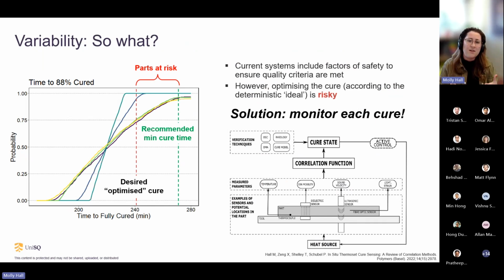Our current minimum cure time for this material, with this cure cycle, is about 275 minutes. So at that point, we're expecting that all of our parts are going to be sufficiently cured, and there's not really a risk there. That's our factor of safety to ensure that all of these components are cured. However, there's always a push to optimize our cure and optimize production time and manufacturing time. And the number that commonly gets thrown around is a 30-minute reduction in cure time. So if we're trying to reduce this to 240 minutes, there's this whole section of parts that are at risk of not being fully cured. And that does introduce risk to our process.